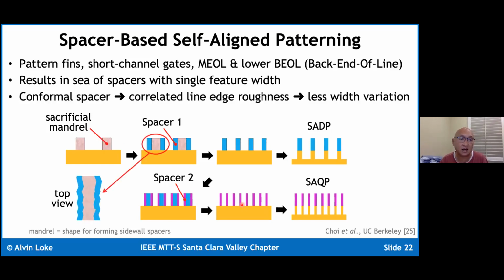One of the side benefits of using this spacer-based approach is that because the spacer deposition is conformal, your line edge roughness for each hard mask feature, or for each spacer, is correlated between left and right edge, which results in less width variation.